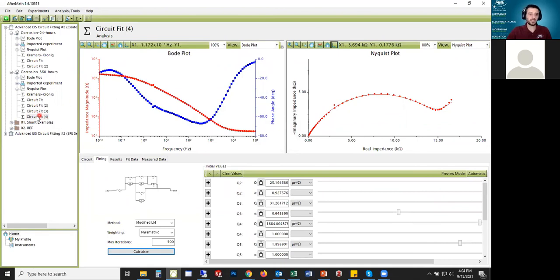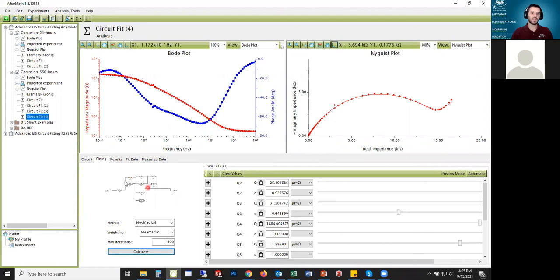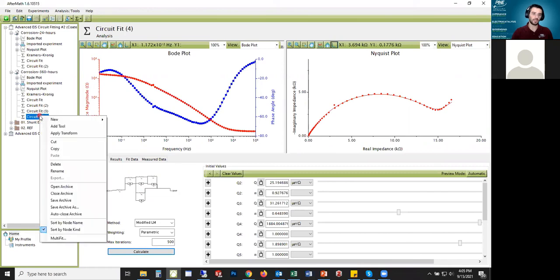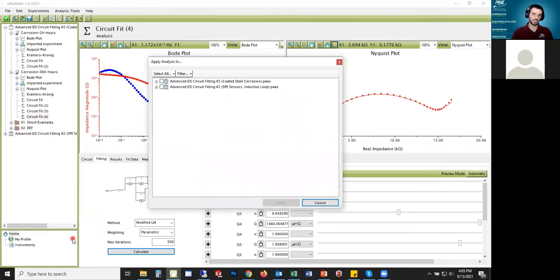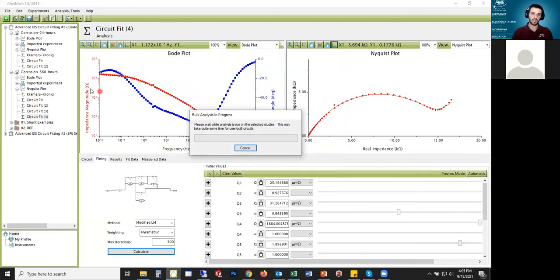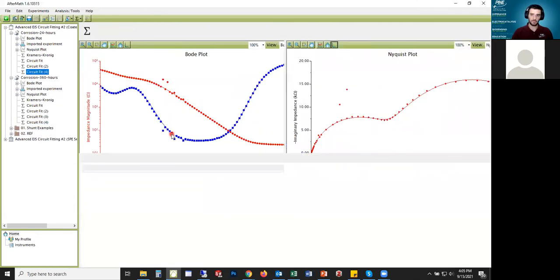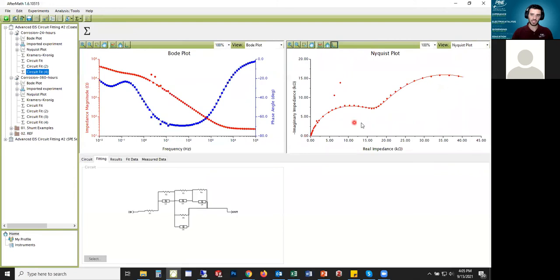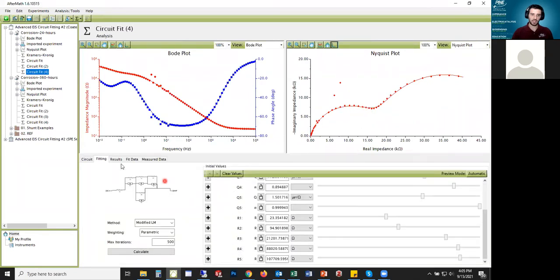The last bit that I'm going to do here is quantitative analysis. I'm going to show you how you can get a numerical approximation of the corrosion rate. But to do that, I want to compare apples to apples. I want to look at the corrosion rate of 24 hours versus 360 hours. So I want to apply this same circuit fit so I can compare the same resistors on both of them. What I'm going to do is I'm going to do multi fit, which is just a batch fitting, and I'm going to select the data set that I want, which is the 24 hour. It's going to use this same circuit fit and automatically apply it. And it looks like it did a pretty good job of fitting.